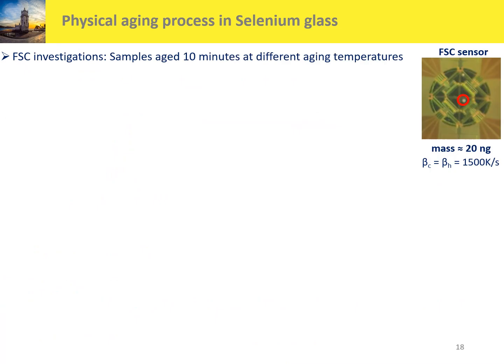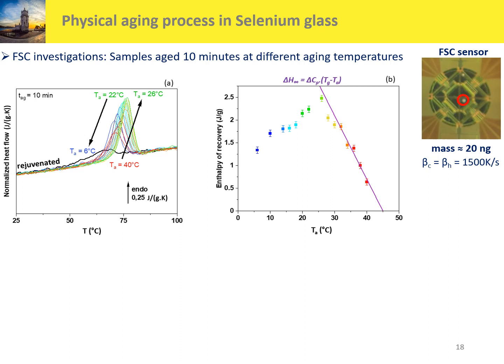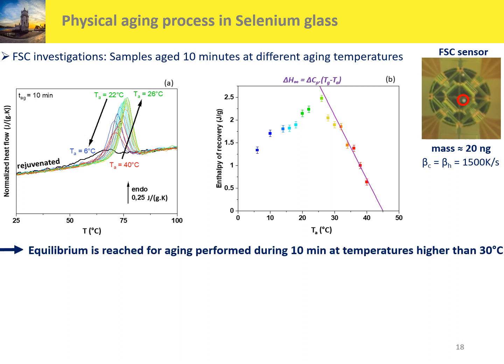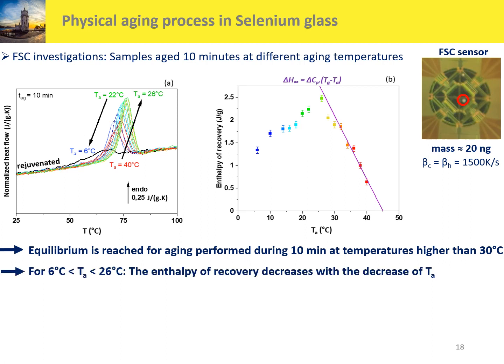After this, we performed fast scanning calorimetry investigations on the selenium glass. The samples are aged 10 minutes at different aging temperatures. We observe this kind of experimental curves, and for each aging temperature, we calculate the enthalpy of recovery. As you can observe here, the equilibrium is reached for aging performed during 10 minutes at temperatures higher than 30 degrees C, and for aging temperatures between 6 and 26 degrees C, the enthalpy of recovery decreases with the decrease of the aging temperature.